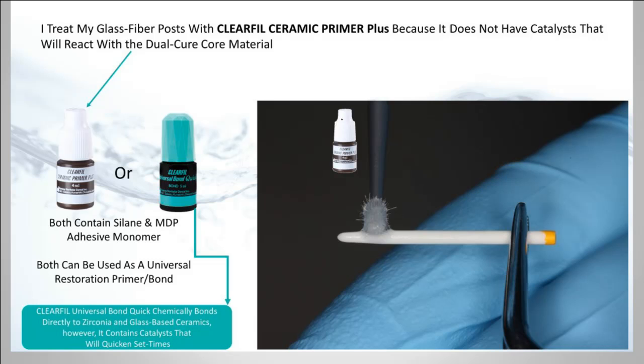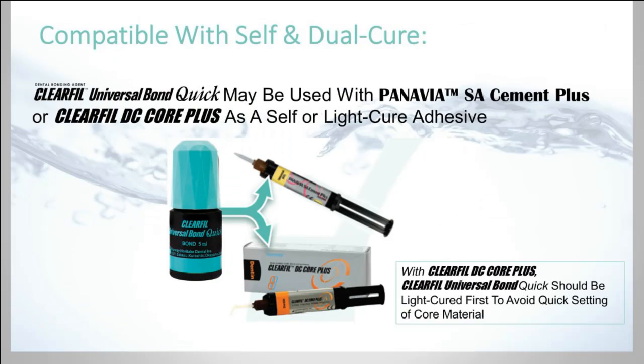And then you've got a choice here. You can either use the ceramic primer as your silanating agent. It doesn't have catalysts in it, and so it won't make the dual cure material go faster. Or you can use the Clearfill Bond Quick. Both can be used as a universal restoration primer bond on the post. Either one of those will work great for you. I kind of like having one bottle in the room because there are fewer things to mess up. And the Clearfill Universal Bond Quick chemically bonds directly to zirconia and glass-based ceramics. However, it contains catalysts that will quicken the set times of your dual cure materials.